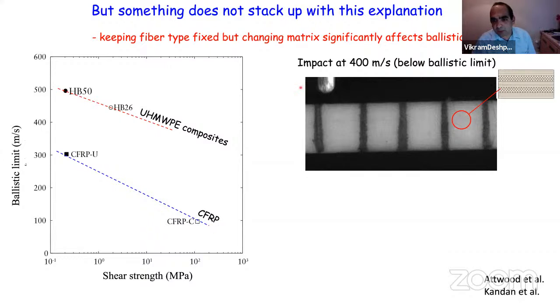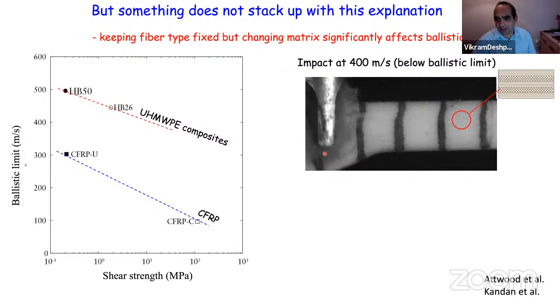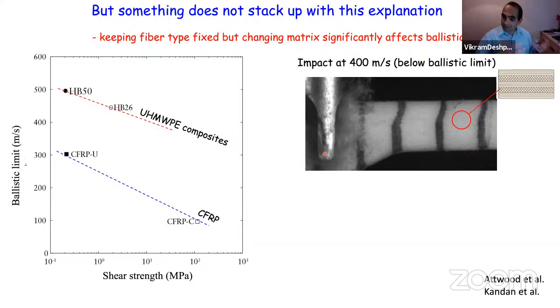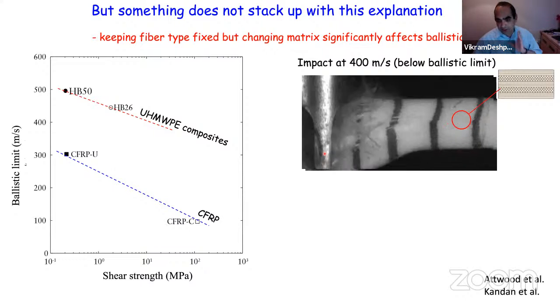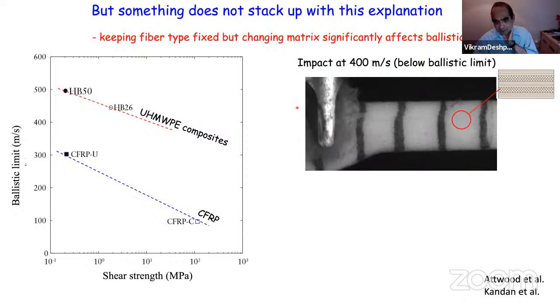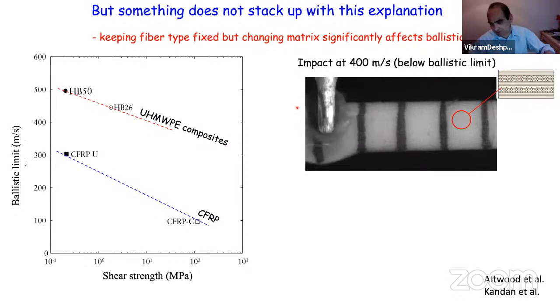So if you now do this experiment, so this is impact of that ultra-high molecular weight polyethylene composite beam with this kind of architecture, and look what's happened here, is that you're getting failure here underneath the projectile when there is no wave that has propagated, nothing that has happened, and it's just uniaxial compression-like failure. Hardly the back surface has moved either. And then as you go on further, you see that this beam is shearing a lot. And so maybe the shearing is important as well. So really speaking, failure seems to occur by just a through thickness compressive strength and none of this complication of bending, etc.